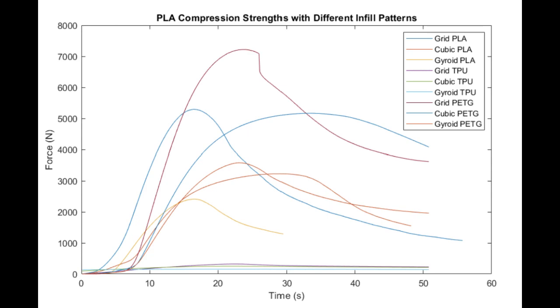For the grid and gyroid infill patterns, the graph shows a sharper incline and decline in force. However, for the cubic infill pattern, the force inclines at a slightly less steep angle and does not drop off after the maximum nearly as much as the other infills. A conclusion that we can draw from this is the infill pattern is likely collapsing on itself and increasing the compressive strength after the maximum force has already occurred.